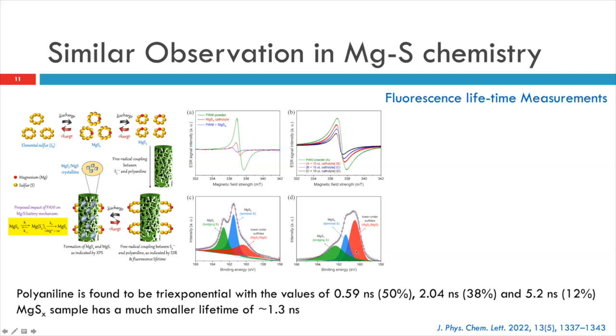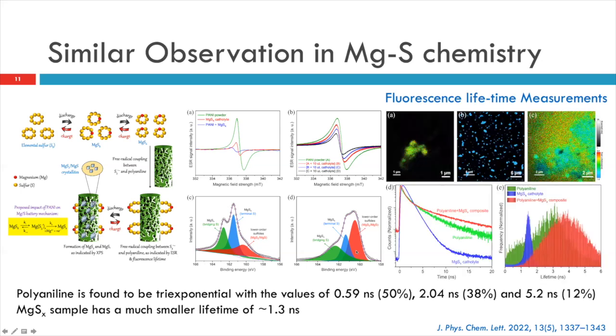We thought maybe an electronic conductor is required, from our previous report. But here, when you start looking at this free radical mechanism, once you observe it with sodium sulfur, we thought maybe we should look at the other work where we have observed this, to see whether it is correct and whether it is validating for other sulfur reactions. So here also you see the same thing. The same explorations are going on here, but additionally we have done some lifetime experiments to see whether the lifetime of the free radical is matching or not.